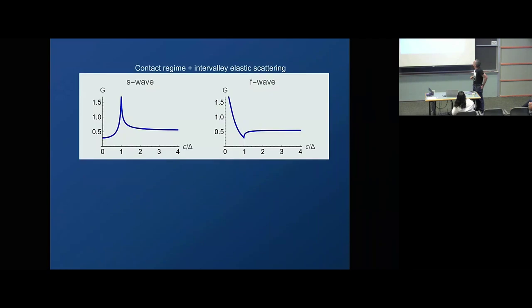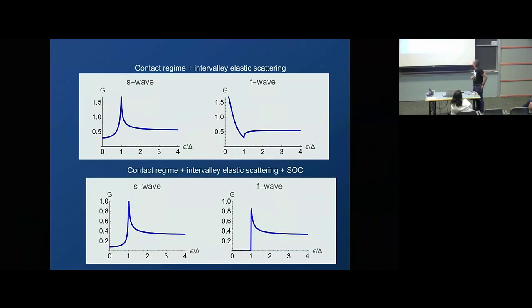But you can have something else. If you have an F-wave superconductor and you bring a tip close to it, the tip can induce transitions from valley to valley. The tip is also a scalar perturbation, and that will create extra Andreev states inside the gap. And if you add those extra Andreev states, you can have peaks which resemble Andreev scattering, but that's because the tip itself is perturbing the superconducting phase.